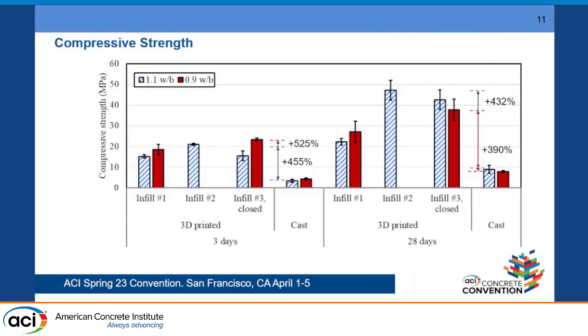So very quickly, we can look at the compressive strength results. At 3 days of carbonation, so these are specimens that were cast or 3D printed, left for 1 day, then placed in a carbon chamber to carbonate. At 3 days, we can see that all 3D printed specimens have significantly higher compressive strength. We're seeing increases from the cast specimen, and those are the carbonated ones, between 400 to 500%.